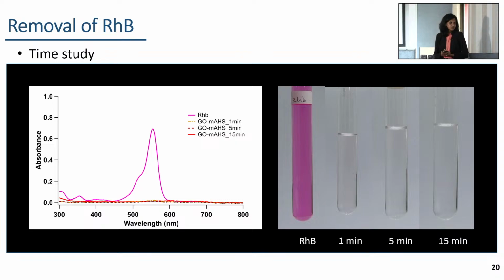Then this GO-based composite was analyzed for rhodamine B dye removal for different time periods, and here I have shown the UV-visible spectra of the filtered solutions after the rhodamine B adsorption process. We can see that this GO-based composite shows efficient dye removal even within 1 minute contact time. This shows the high dye adsorption performance and efficient dye removal capacity of this composite. At the same time, it shows efficient gravity separation. Therefore, we can use this composite to remove rhodamine B dye and separate it without adding any coagulant or flocculants.